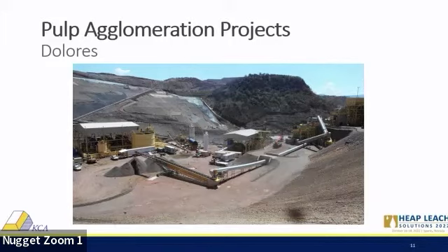The slurry was pumped to 3 pressure filters operated in parallel. The resulting filter cake was combined with low-grade ore in a mixer before being fed to the agglomeration drum, where it's then recombined with low-grade ore from the existing heap leach crushing circuit and conveyed onto their leach pad. The filtrate from the filters was clarified using a pin bed clarifier to remove any suspended solids and then pumped to their existing Merrill-Crowe facility.